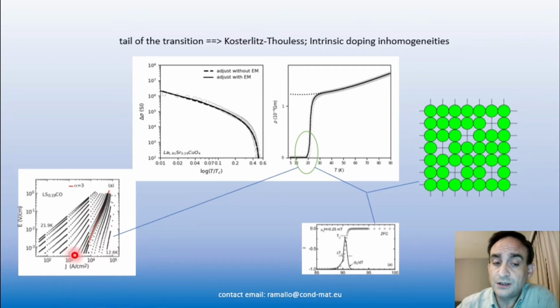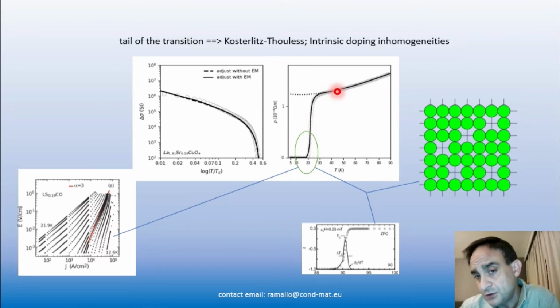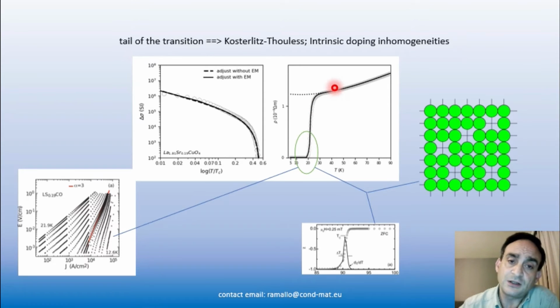And then there is the very famous Kosterlitz-Thouless transition that happens in the tail. The Kosterlitz-Thouless transition temperature, you can actually measure rather easily just with the voltage versus current curves. When you see the appearance of non-ohmic effects, if you have a slope here of 3, there is a famous result by Halperin and Nelson identifying very precisely that temperature with the occurrence of the Kosterlitz-Thouless transition. So with this taken into account, you obtain this beautiful agreement of experiment and theory.